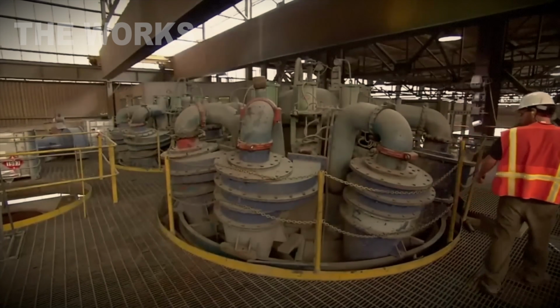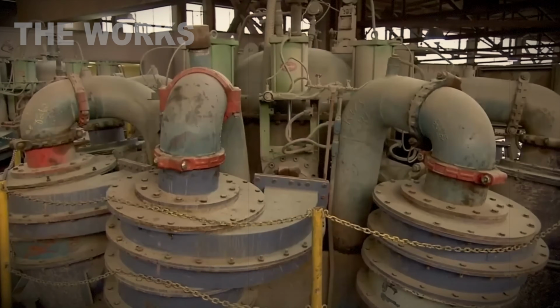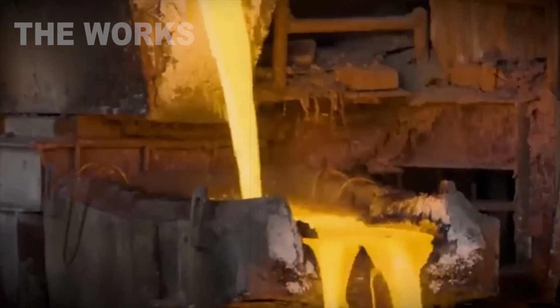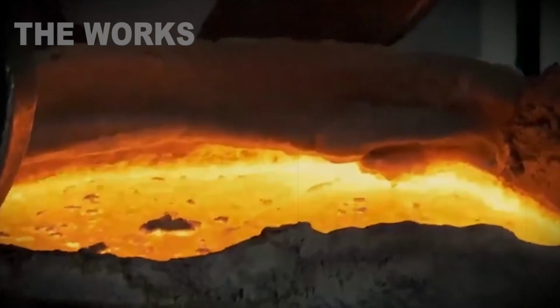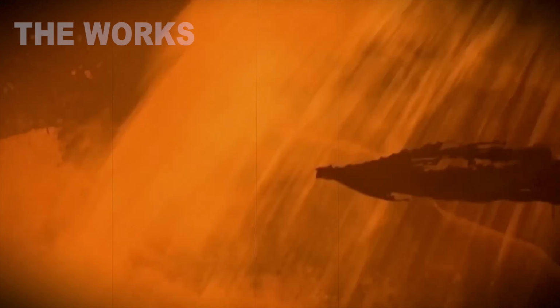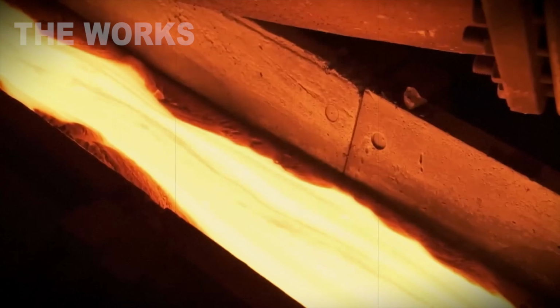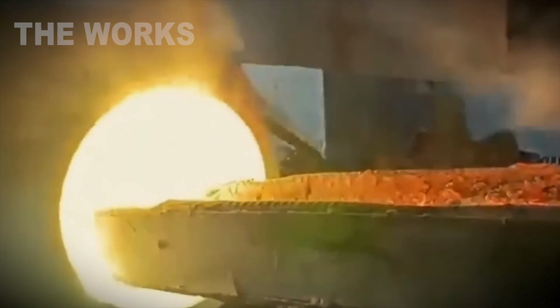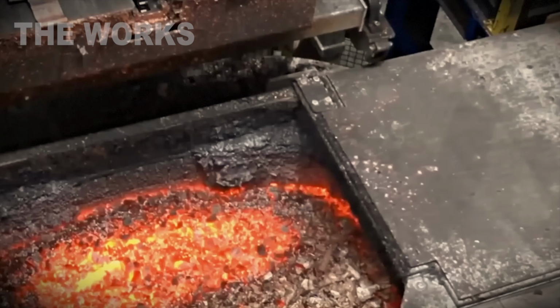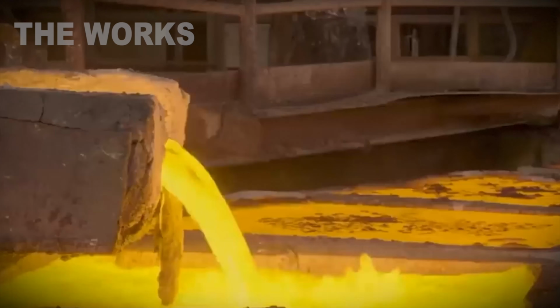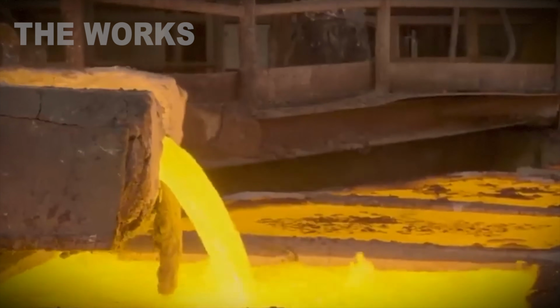The concentrate ships to the copper smelter in Głogów, one of KGHM's 2 plants. They use a single-stage flash smelting technology. The concentrate gets dried to 0.3% moisture and fed through a burner into the smelting furnace shaft. At the same time, they blast oxygen in. Not air, but pure industrial oxygen at 95% purity.